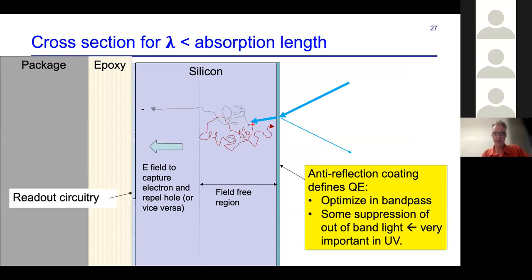So we've got the back surface on the right, and the electrodes or circuitry are on the left here. It's bonded usually with epoxy onto some usually metallic package, or it might be silicon carbide. But we've got some layer of silicon. In CCDs, they might be as much as 250 microns thick. For an ultraviolet sensor, you might be down to only 5 microns. So a photon that makes it through the AR coating generates an electron hole pair close to the back surface.